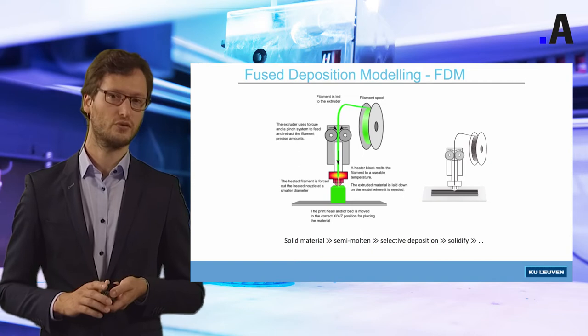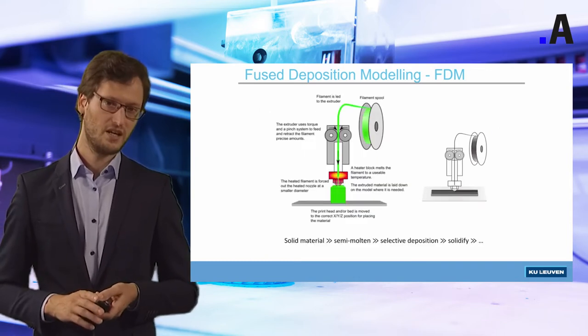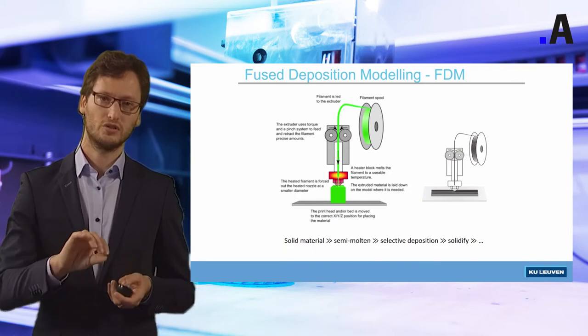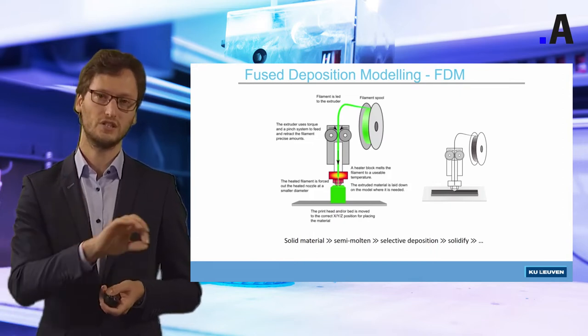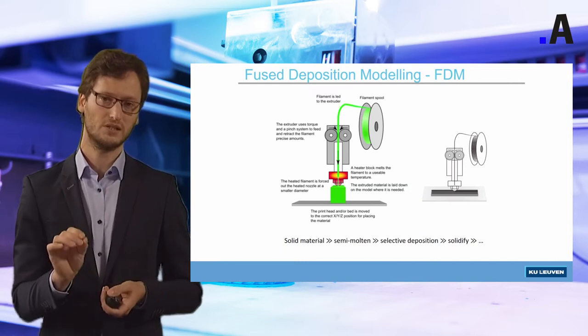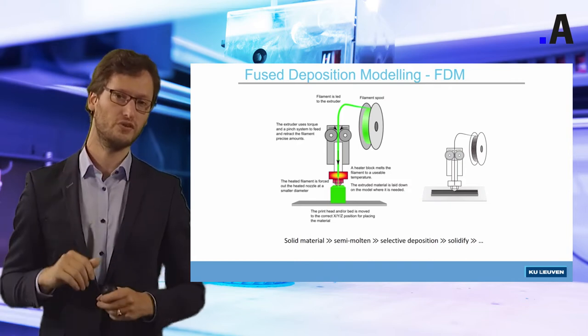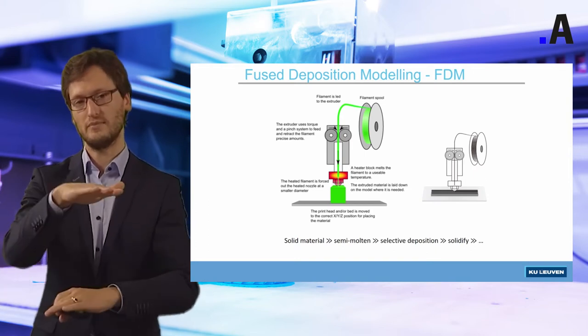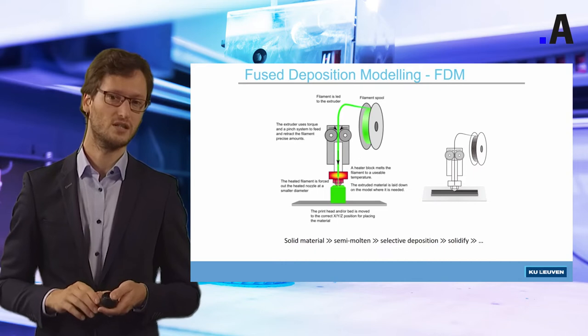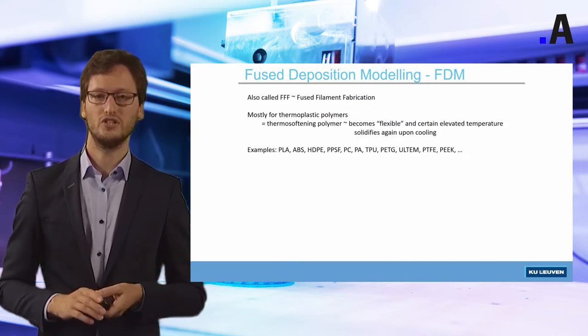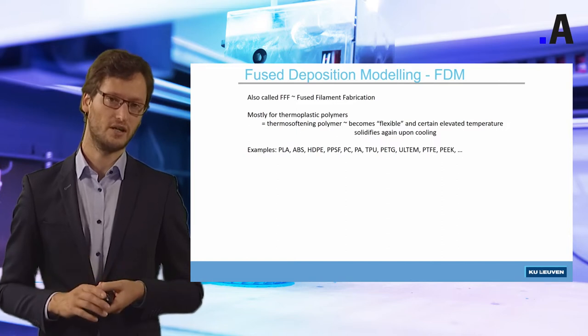The second technology for processing plastics is fused deposition modeling, also called fused filament fabrication. It starts with a very thin filament of polymer that is fed through a nozzle. In the nozzle, this filament will melt to a semi-molten state that can then be deposited on a base plate. Either the nozzle or the base plate can move in X, Y and Z directions, and by programming the machine you can print complex parts. Support structure is also needed when printing overhanging surfaces. These technologies are mainly used for thermoplastic polymers.